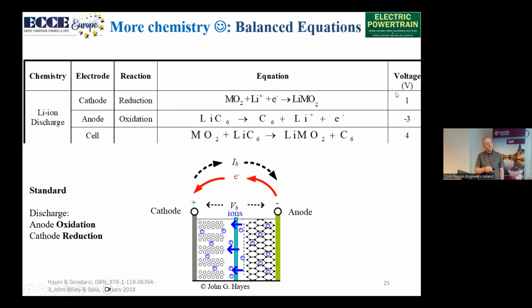And that half cell voltage is going to be 1 volt. We subtract the two from each other and we get an overall cell voltage of 4 volts. And that's pretty much as high as we can go. Well, I'll put a caveat on that. But we're achieving the full potential of lithium, and the only thing above lithium is hydrogen. And we're only using that in fuel cells.